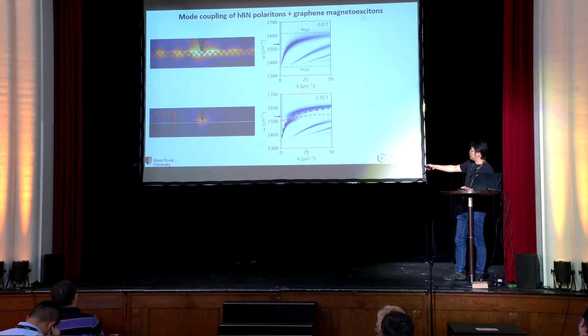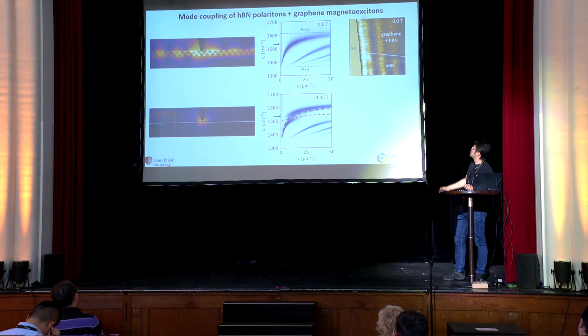So this is, the red one is the magneto-excitons that is tunable. The black one is just the original phonon polaritons. You can see a clear gap here. So in the experiments at 0 T, we see that in graphene-hBN, this polariton is launched by this gold antenna, no problem.